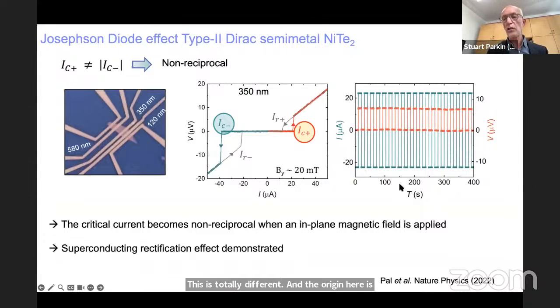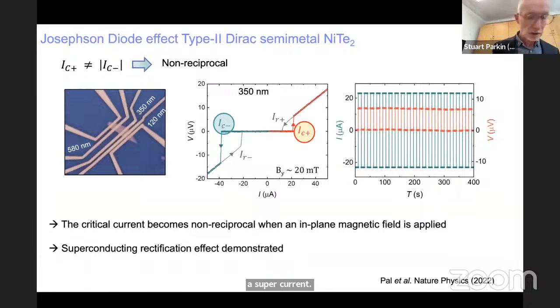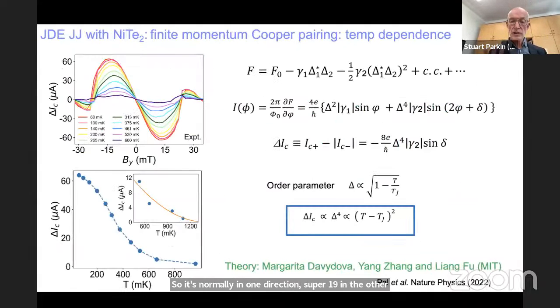What it means is, as shown on the right-hand side, you can see that when the current flows in one direction, which is the blue, switching from minus 25 to plus 25 microamps, the voltage only appears for the current flowing in one direction. For the other direction, the voltage is 0 because it's a supercurrent. So it's normal in one direction, superconducting in the other direction. So it's a very interesting non-reciprocal effect. And we think we understand this pretty well in a collaboration with Liang Fu and his group at MIT. We showed this was due to finite momentum Cooper pairing that I mentioned earlier. But here, it's due to the spin polarization of these surface states.